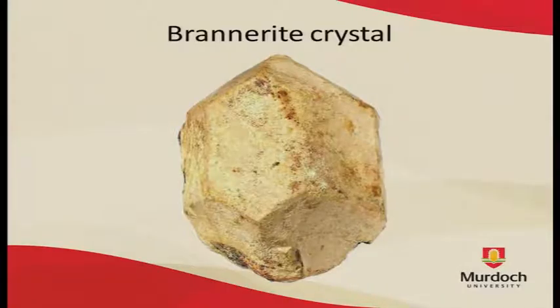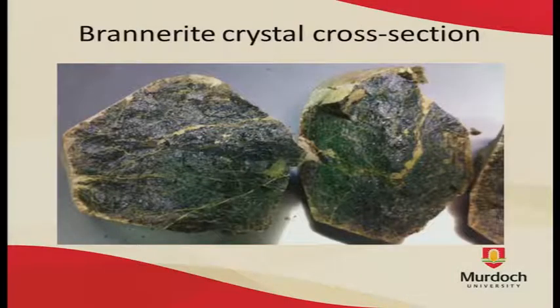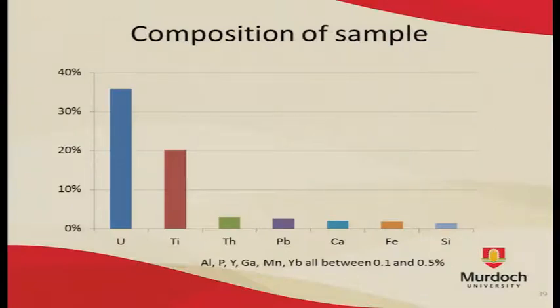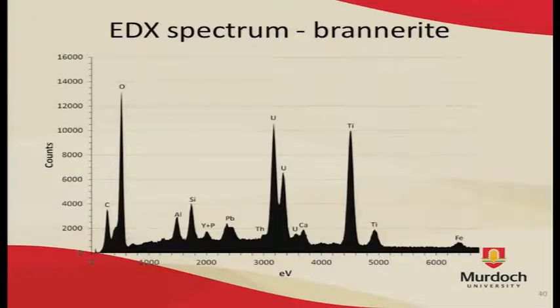And that was a sample, just a crystal of uranium brannerite. Brannerite itself is quite a dark brown to black colour, but it's coated in a white alteration layer, which is apparent from this photo taken not long after the crystal was cracked open. Dark brannerite coated in a very thin, light-coloured alteration layer. The brannerite was not too highly substituted. It's fairly pure. It's mostly uranium and titanium, some thorium, lead, calcium, some other minor impurities as well. And the EDX spectrum agrees.